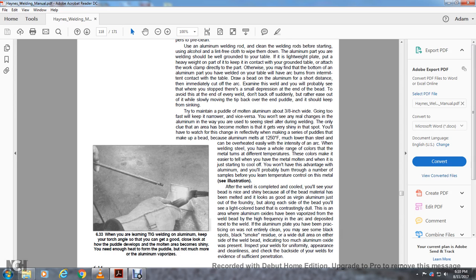You will want to watch for any change in the aluminum as you weld. The only indication that an area has become molten is a very shiny spot. You will have to work on the change of the reflections in the puddle to build up the bead, because aluminum melts at about 1250 degrees Fahrenheit, much lower than steel, and can overheat easily with the intensity of the arc.